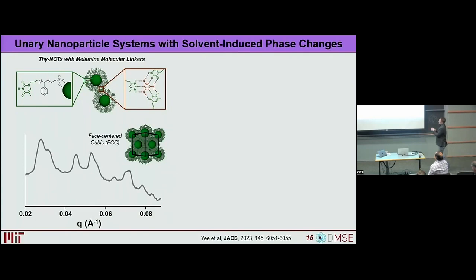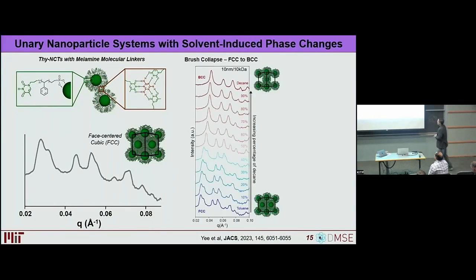And what we see is we get an FCC lattice because this is the densest you can pack spheres of a single size. What's interesting about this, though, is that when we try and look at these under the microscope and we do that solvent exchange process, we get a phase transformation. We start out as FCC, and as we slowly increase the percentage of decane we add, at a certain point, we flip to BCC.